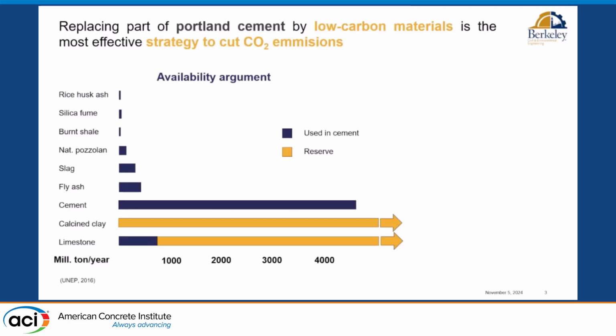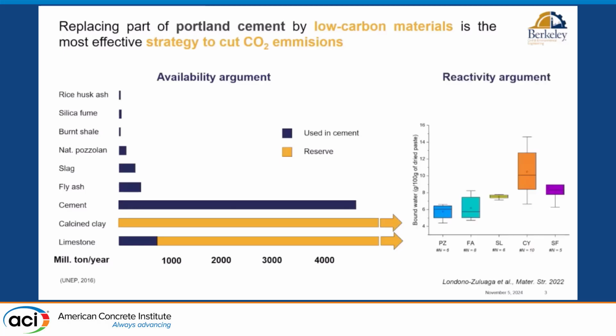And you need to imagine that these are figures from 2016, this is dynamic, and the demand of cement is actually growing, and is growing not in the developed world, not in the global north, but actually in the global south. And the second reason to use calcined clay is because they are just reactive. They are much more reactive than other SCMs. This is the heat release that we obtained by the ASTM C1897 method, or R3 test. And you can see that calcined clays are significantly more reactive, on average, this is more than 100 materials that we tried, than natural pozzolan, fly ashes, and even slag.